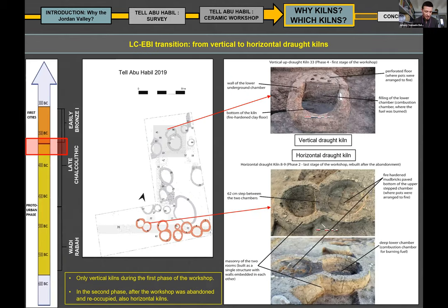Because at Tell Abu Habil, between the end of the Chalcolithic and the very beginning of the Early Bronze Age I, there is a transition from a phase in which there are only vertical kilns in the workshop to a phase in which there are both vertical and horizontal kilns. Between these two phases, there is an abandonment of the whole area, the whole site, all the firing structures, and the workshop was no longer in use.